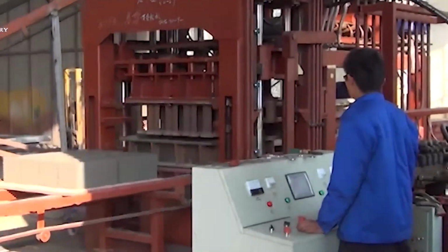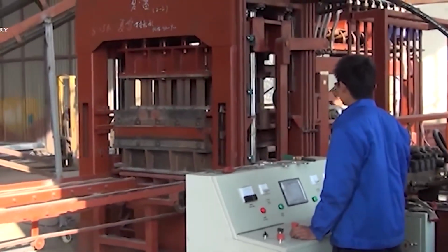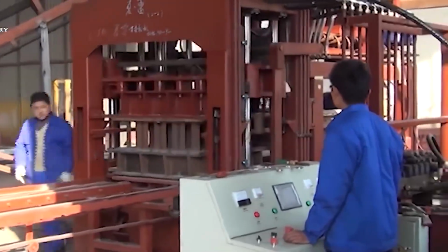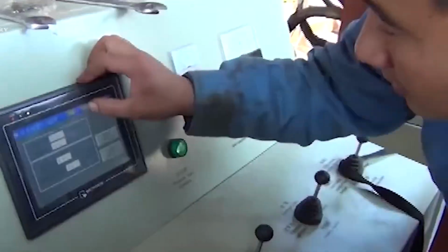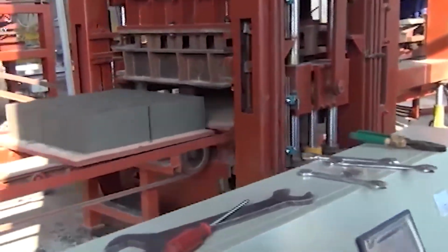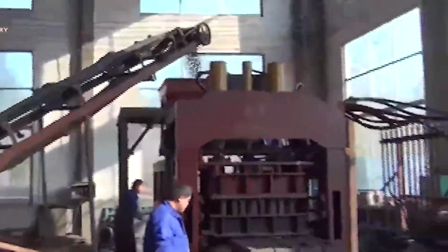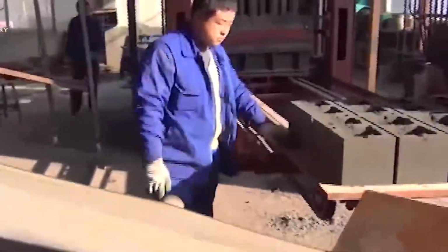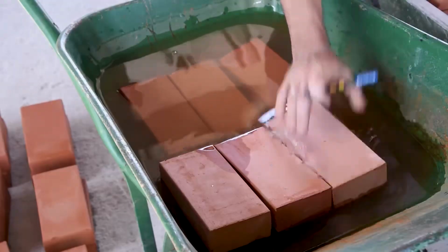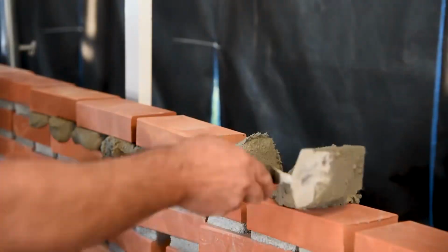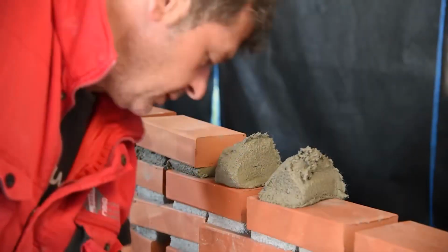And what are the practical differences that influence the choice? Here come the fundamental properties that every designer and builder evaluates. The concrete block generally offers greater compressive strength than the common ceramic brick. Structural blocks can reach characteristic strengths above 4 MPa and up to 8 MPa or more, according to NBR 6136. Solid or good quality ceramic bricks can get close, but common hollow ones often range from 1.5 MPa to 3 MPa,